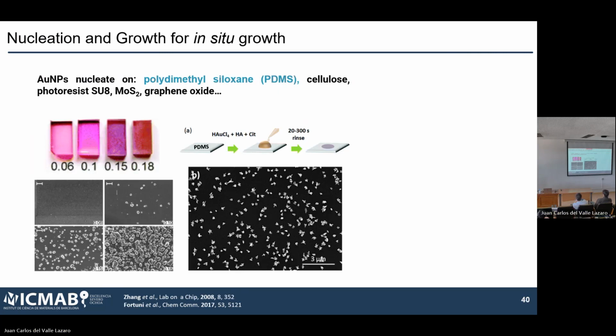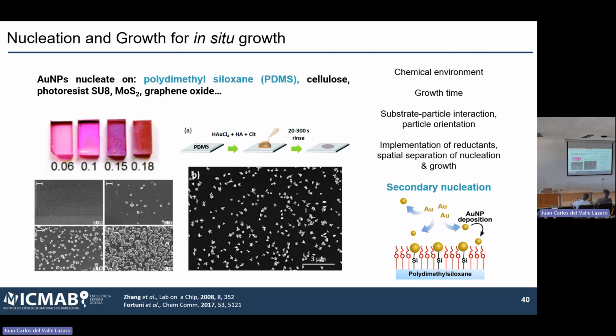Okay? And the other thing that you need to know about in situ growth, and that makes it extremely hard, is that you always have a moment where you have your material where you want to grow your particles, and you have to expose it to a solution containing all the chemical elements that you need for the growth. So you always have to be aware that you need to control and possibly avoid what we call secondary nucleation or homogeneous nucleation. Basically, if you want to control what you have on your sample, you have to make sure that the particles on the substrate grow directly on the substrate, and are not growing in solution and then depositing on the substrate. Otherwise, you're not controlling them. So controlling secondary nucleation is probably one of the most complicated things.